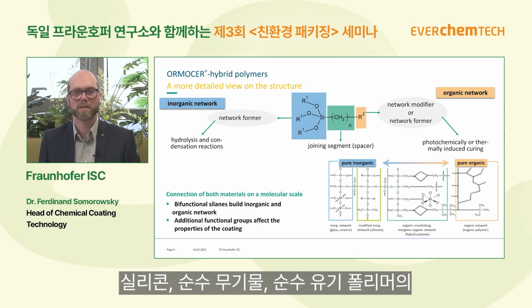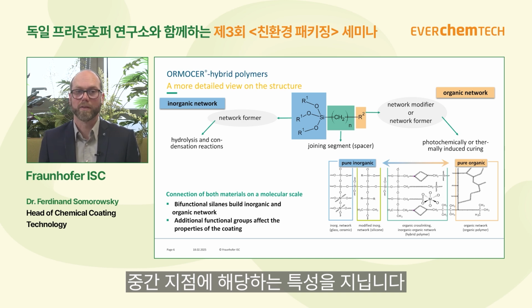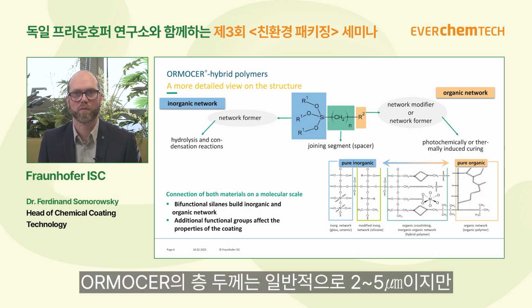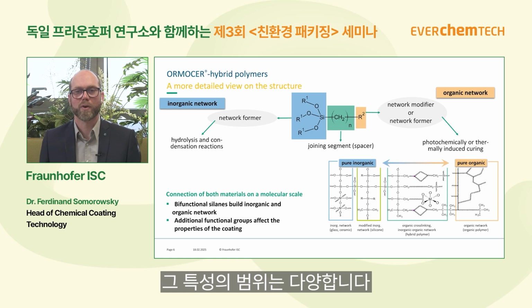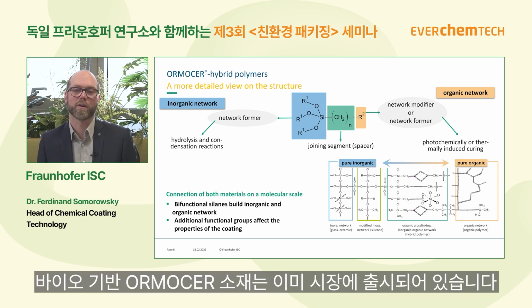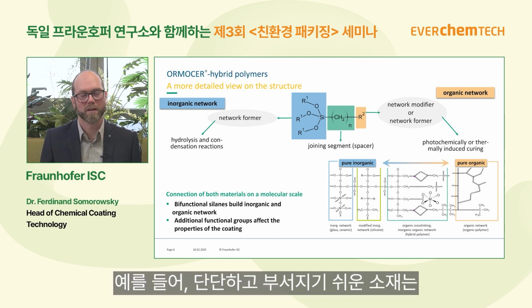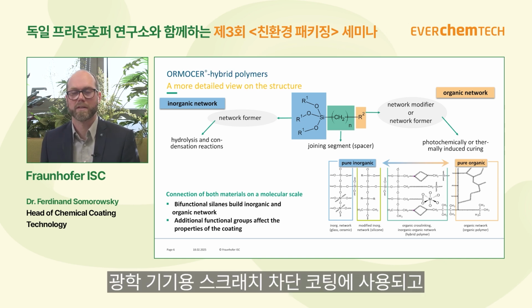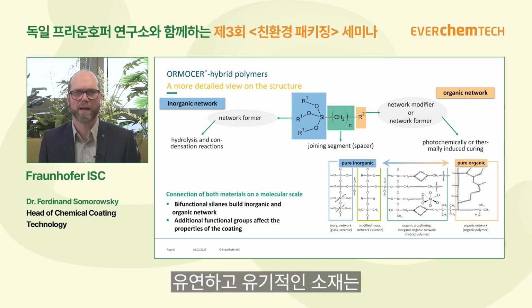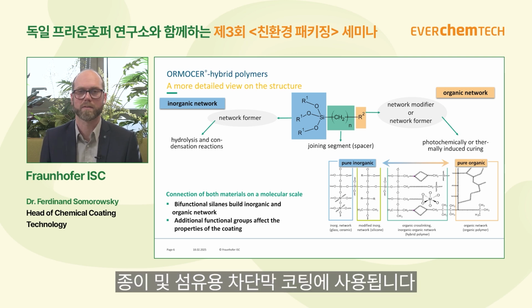When we look into the properties of ORMOCER, they are a little bit in between silicone, pure inorganic materials, and pure organic polymers. The typical layer thickness for ORMOCER is between 2 and 5 micrometers. But there's a huge range of properties. There are ORMOCER materials already on the market which are very hard, very brittle, for example, scratch-resistant materials for optical devices. And then on the other side, barrier coatings for paper or also textile coatings. So very flexible, very organic material, and that's all ORMOCER.